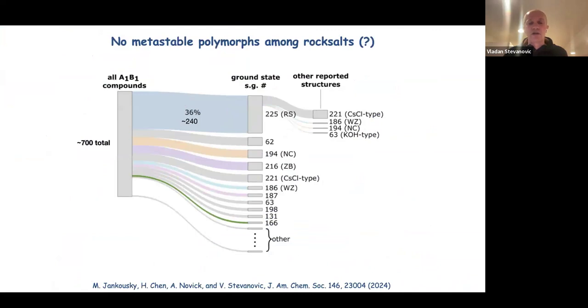And this is the result of our literature review, where we investigated all A1, B1 compounds, searching for those that crystallize in their ground state as rock salt. There are about 700 total in various databases of A1, B1s. 36% of those, about 240, are actually known to crystallize as rock salts in their ground state. By the way, A1, B1 is the largest known group of compounds by far, and the rock salts is the largest group of compounds, even beyond binaries, that all crystallize in one crystal structure.